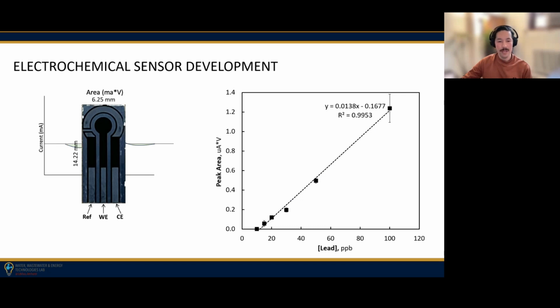So this is some work that we did in the lab, and we do get a nice linear line. From this experiment, we are getting limits of detection at around 5 ppb and limits of quantification of about 15 ppb. So for EPA, there's a Lead and Copper Rule, but the maximum allowable concentration level is 15 ppb. So from a federal governing standpoint, systems need to be under 15 ppb. So our limits of detection are right around those EPA MCLs, which is great.